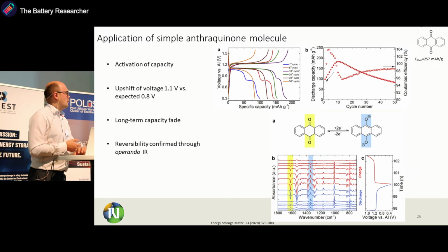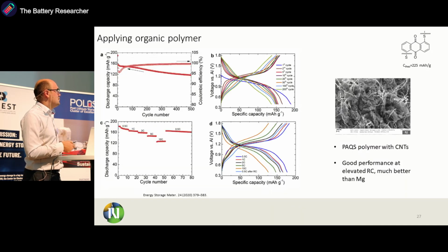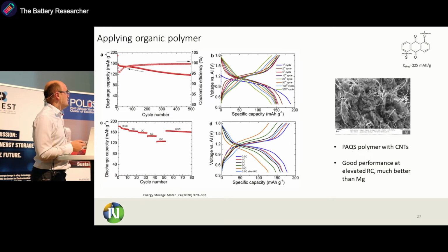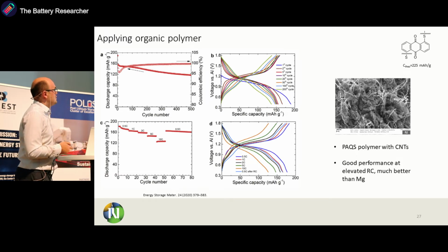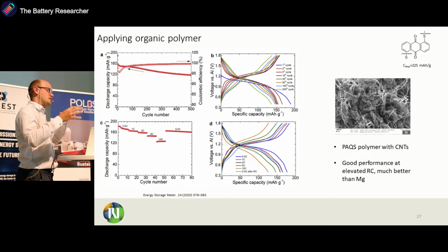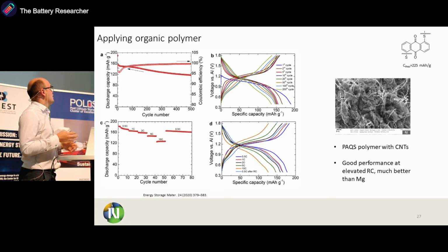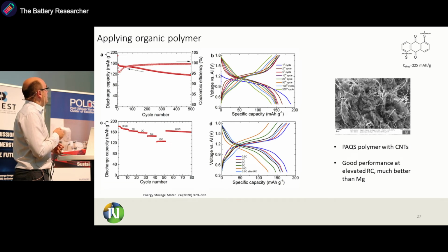So we wanted to improve the long-term capacity retention, so we decided to prepare polymers. And again, we relied on PAQS polymer with CNTs. And we could see that basically we get much better performance because we added CNTs. Also, the accessibility of electroactive groups is much better. And we obtain already in the first cycles 190 milliamp hours per gram, and then we have quite fast fade, but quite stable performance. And after 50 cycles, we still get more than 120 milliamp hours per gram of capacity.